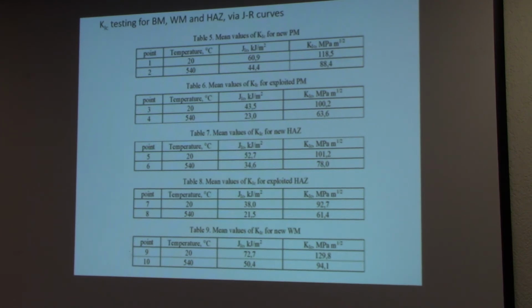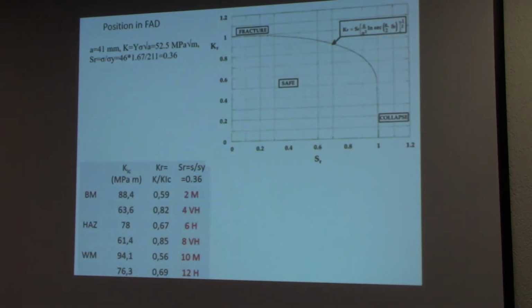Critical, you can see at once, would be this at the 540. So if we keep in mind that K is something that we calculate and then we divide it by the appropriate K1C, we get a set of Y coordinates, whereas the X coordinate is fixed, it is just net stress.